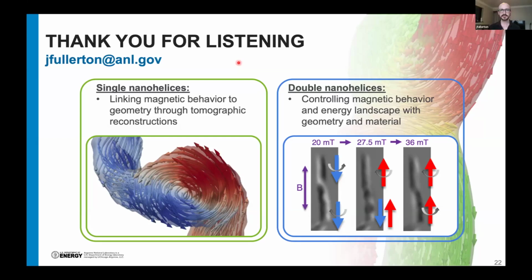Yeah, that's a good question. Cobalt for these kinds of structures is the most widely used one, and that's because you can get these very pure structures, nearly 95% pure. So you're limited by the choice of precursor gas. We've done other work with an iron precursor, which can give similar structures, but is less mechanically stable.